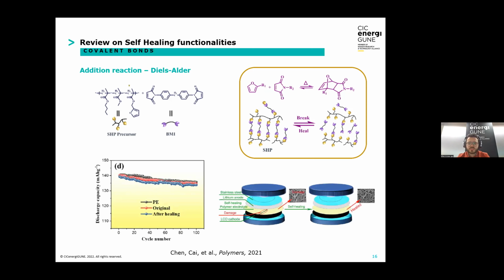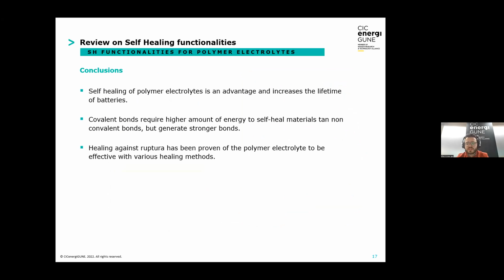In the example, we observed the comparison between a battery with a non-broken and a healed electrolyte, so the red and the blue curves, where the capacity retention is quite similar. Therefore, meaning this Diels-Alder self-healing, it is quite mechanically stable and allows to nearly reach the conditions of the membrane originally had. So overall, self-healing of polymer electrolytes increase the lifetime of batteries through the repair against rupture of polymer membranes. And this healing process is stronger through covalent bond healing, such as the addition reaction. However, it requires a higher amount of energy than non-covalent bonds.